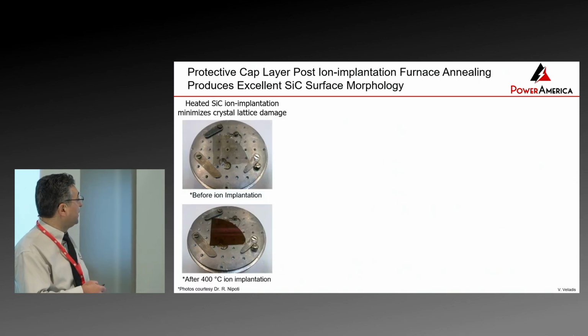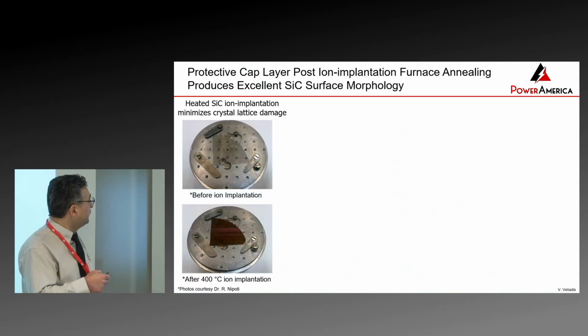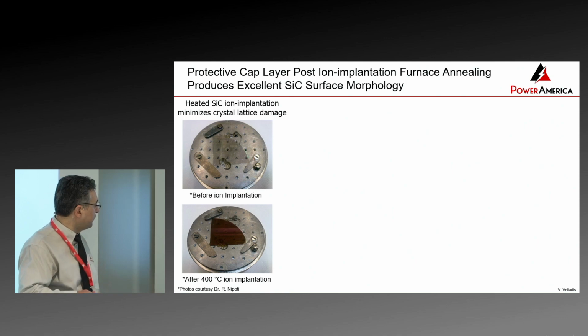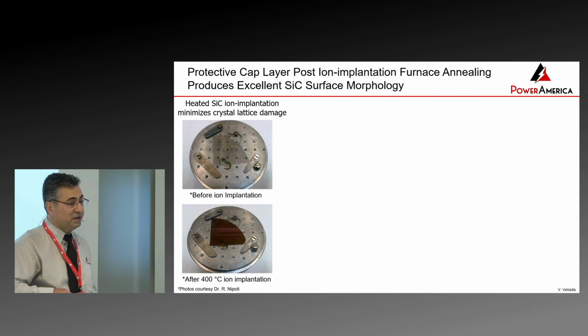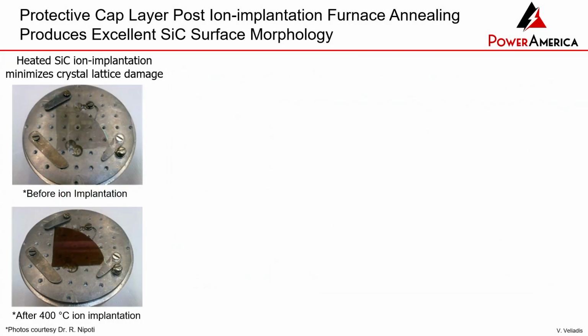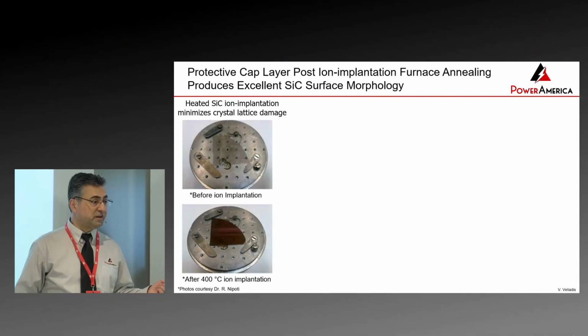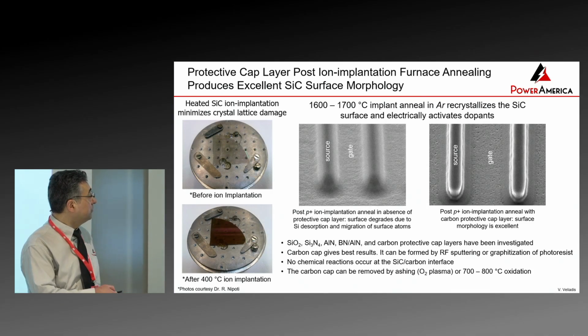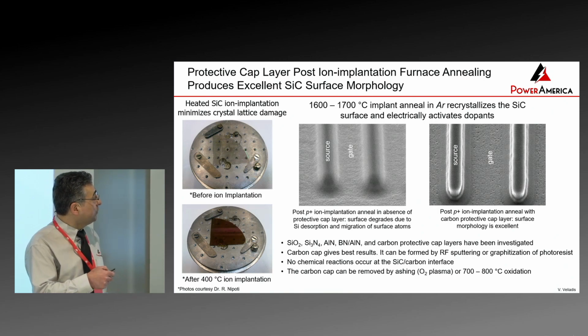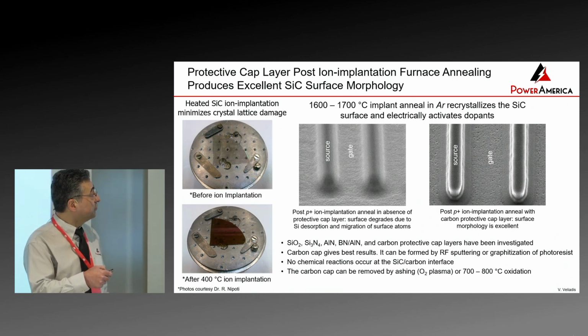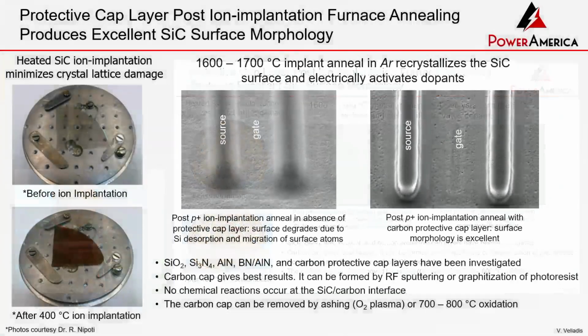Another example is with the implantation. This is before implantation, and this is after the 400-degree heated implantation. And you can see that the wafer now becomes opaque. So you just took a nice crystalline wafer and turned it into glass, despite the fact that you do a heat implantation. What do you need to do next? You basically need to take this wafer, drive it to anywhere between 1600 to 1700 degrees, and anneal it in order for the crystallinity to come back and the dopants to be activated.